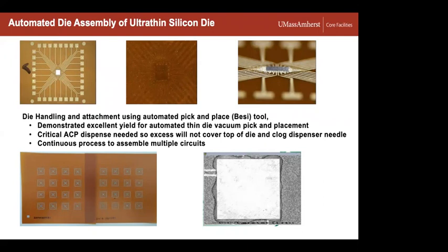And so we did both a lot of assemblies and handling with the ultra thin silicon die. In this case, they were about 45 microns. And the problem there was just handling them at that thickness is you break a lot, you have other stresses and so on. And so we both worked through the handling method, as well as got some very good components now with the Besi tool, where you can very carefully eject these off of a wafer tape.